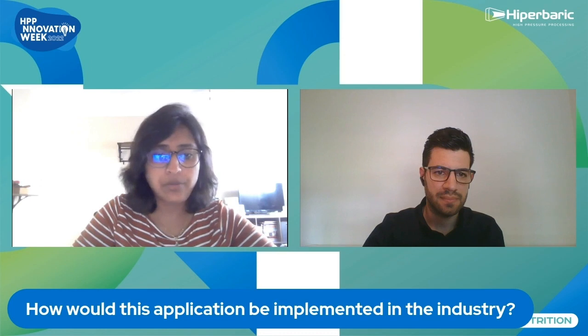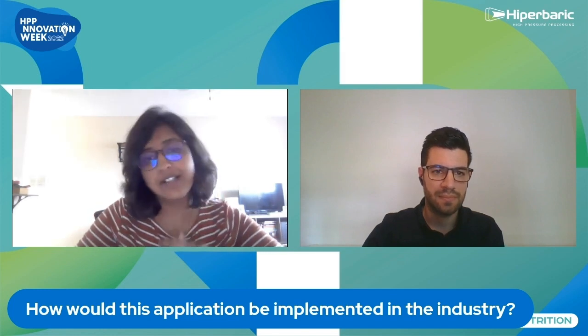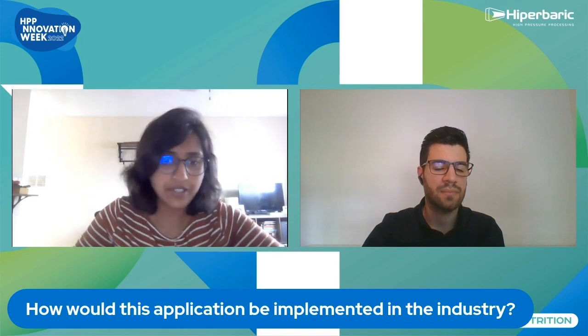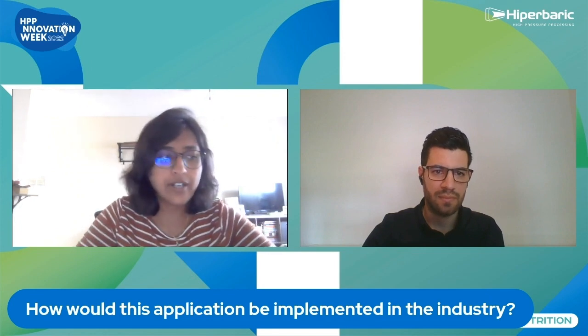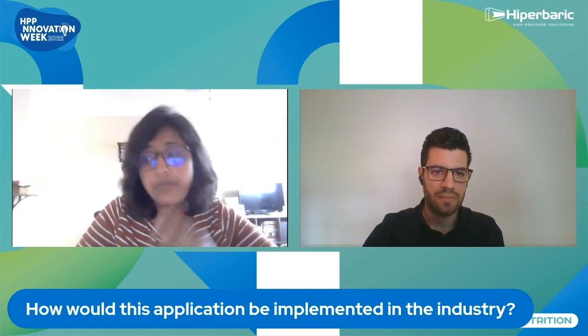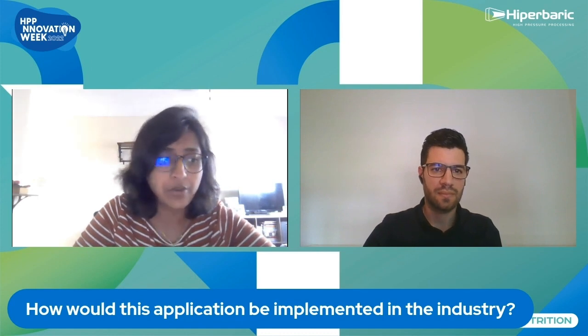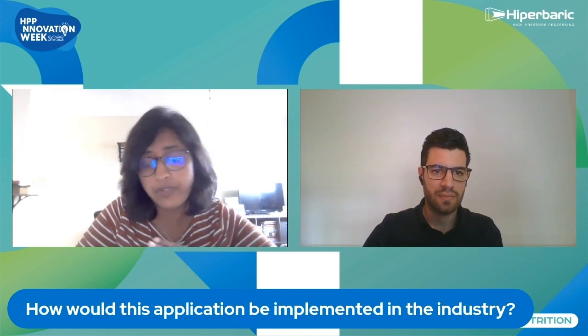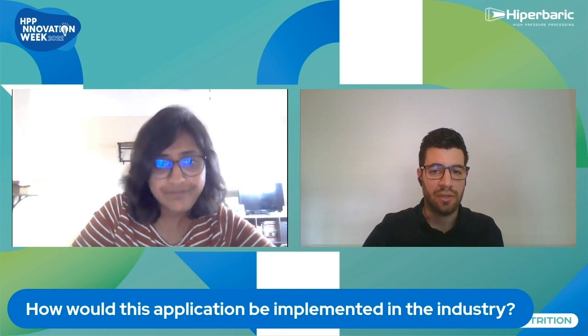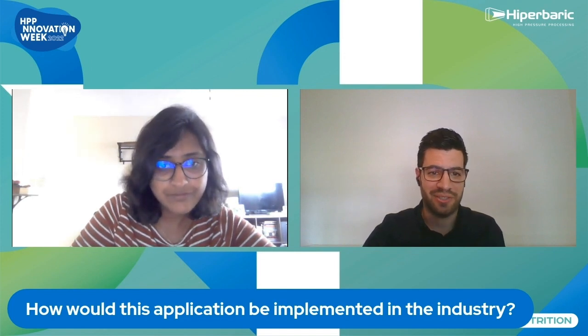If we have enough studying and validation, the way I see it being implemented is if fruits and vegetables could be packaged in a minimal amount of a nutrient solution and the final package goes through a high pressure process. So there is infusion that occurs, but at the same time, you're not exposing it. If you do it as a pre-treatment, you're exposing the package again. But here you wouldn't, and then that would still preserve the shelf life. And we actually did some shelf life studies, and we were able to get some good shelf life data. So hopefully this is scalable. Okay, that's 2-in-1. It's a perfect solution.